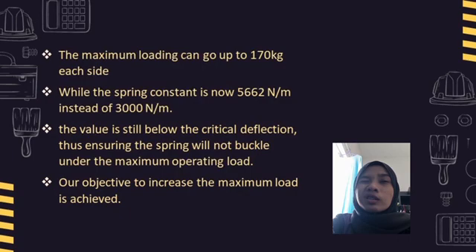Moving on. The maximum loading can go up to 170 kg each side, while the spring constant is now 5,662 Newton per meter instead of 3,000 Newton per meter. The value is still below the critical deflection, thus ensuring the spring will not buckle under the maximum operating load. Our objective to increase the maximum load is achieved.